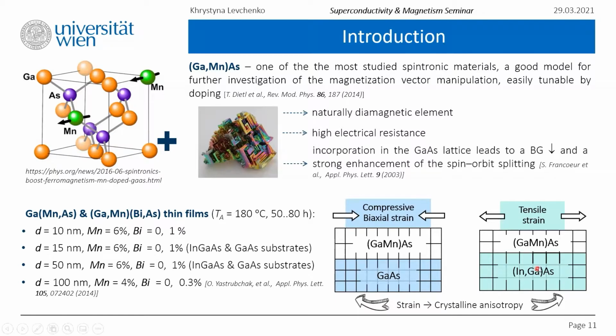In a case where there is a buffer layer, indium gallium arsenide, we are introducing tensile strain. So we are stretching the top layer to fit the lattice parameter of the layer below. Why is it important? Because it strongly influences the crystalline anisotropy, as will be seen further. And we'll have completely different magnetizations, depending on the growth parameters.